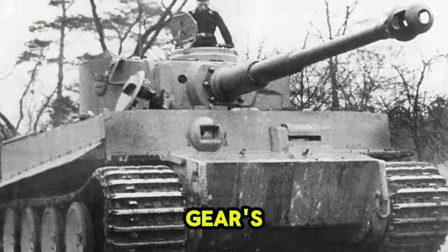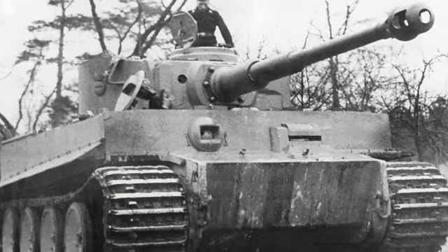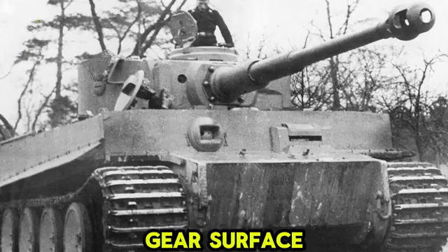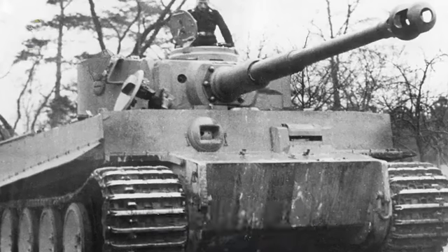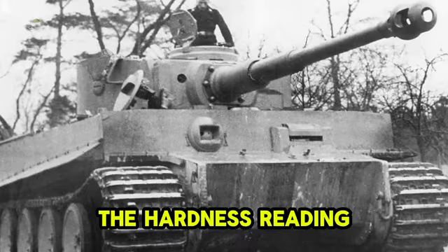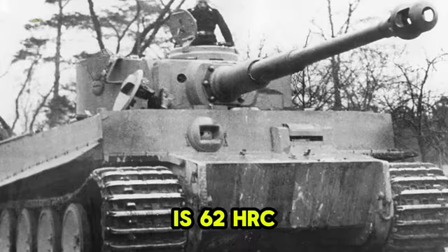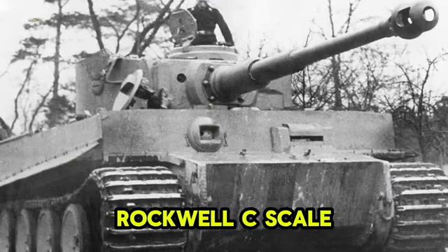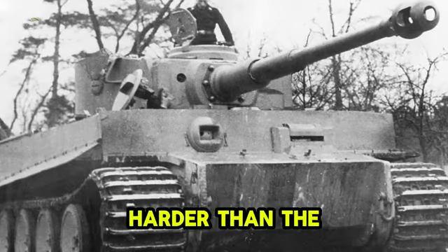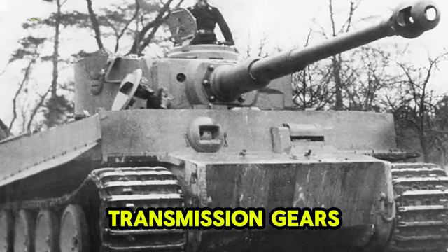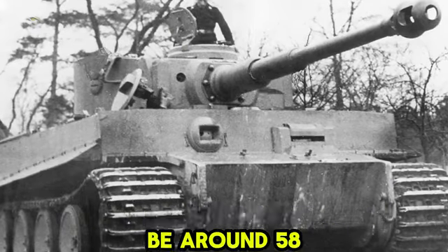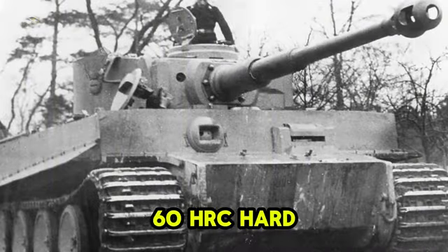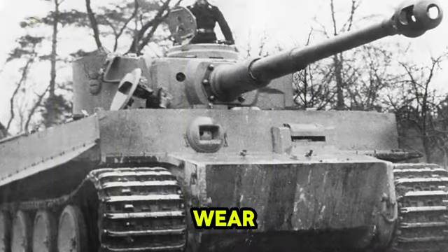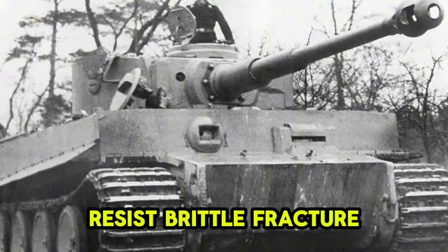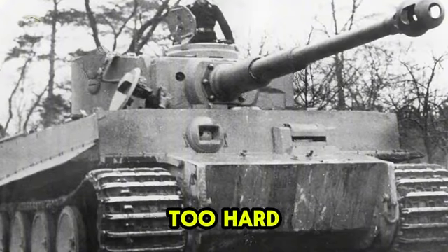Stevenson measures the gear's hardness using a Rockwell tester, presses a diamond indenter into the gear surface, measures how deep it penetrates. The hardness reading is 62 HRC, Rockwell C scale, extremely hard. Harder than the specification for transmission gears. Transmission gears should be around 58-60 HRC, hard enough to resist wear, soft enough to resist brittle fracture. This gear is too hard.